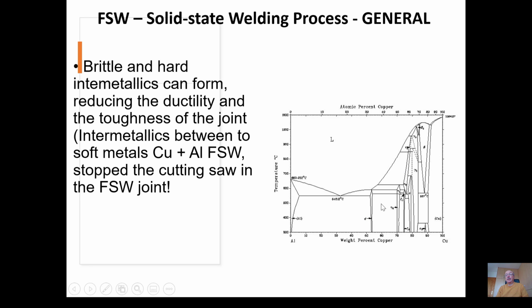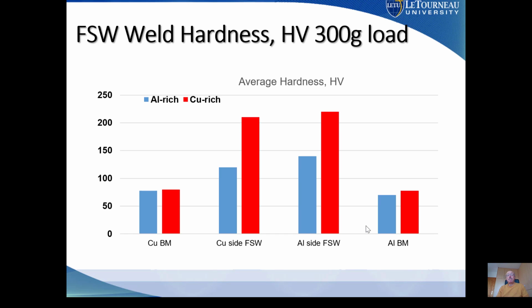And where we are operating below the melting point of aluminum, you will end up with, in this region, depending on the degree of mixing, with different types of intermetallics. And as my text shows there, these intermetallics can be so hard and brittle that they can even stop the cutting saw as a friction stir weld joint of two soft materials. Here's an example. The average hardness of these intermetallics which form can be 2.5, almost 3 times higher than in the base metal. On the copper side, we can see 200, 220 Vickers as opposed to less than 80 in